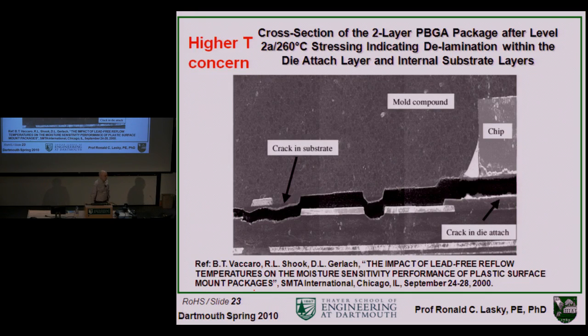The higher temperature, probably of anything for a process person, in addition to the fact that it doesn't wet well, is the fact that the solder for lead-free solder melts at about 34 degrees higher. And in some cases, there are solders that people use that are a little cheaper that don't have silver that melt at 43 degrees higher. And so you're exposing the inside of a package which has a lot of plastic.